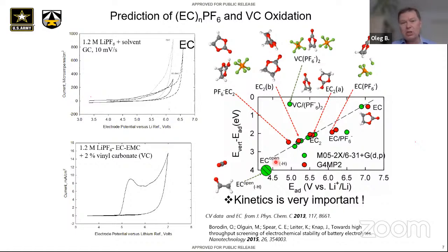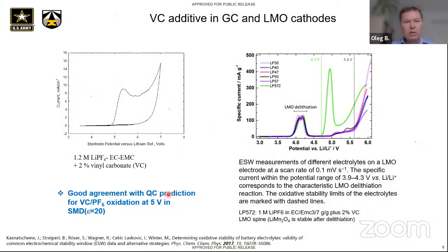So with this in mind, I just want to say that this same trend for VC, a much higher current consistent with much lower reorganization energy, was observed here in CV for glassy carbon, but also in the Mark and Winter group when they used stable lithium manganese oxide spinel and looked at the oxidative stability of electrolytes after intercalation.